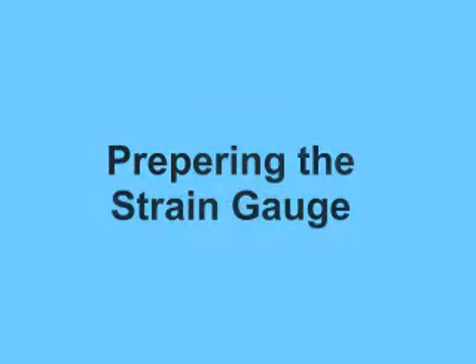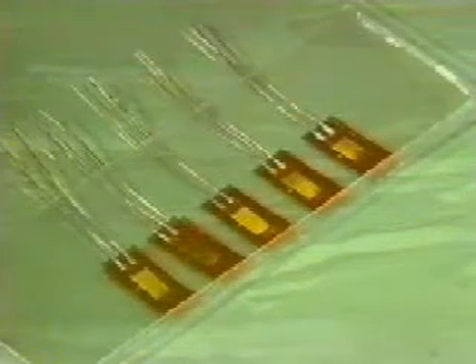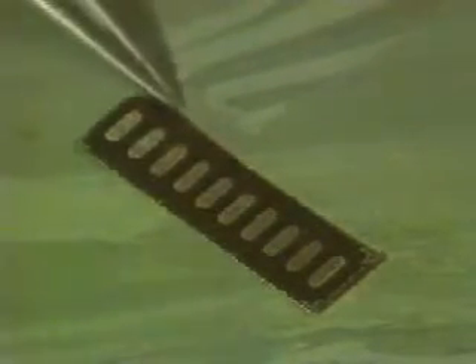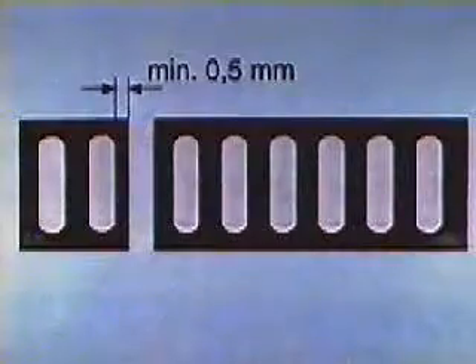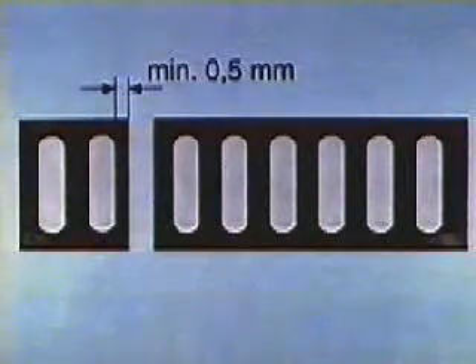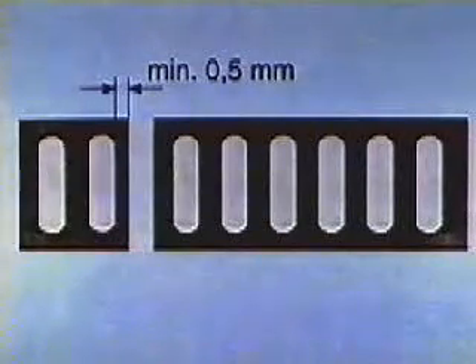Preparing the strain gauge. First of all, the required solder terminals are cut from the strip. Here, an edge of at least 0.5 millimeters must remain for insulation.